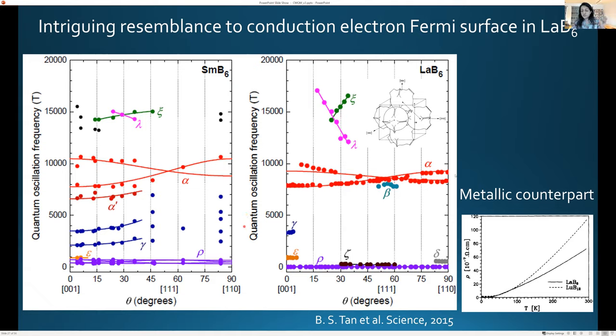So instead, we notice something interesting: the frequency size and the angular dependence is somewhat unexpectedly similar to that of lanthanum hexaboride, which is the conduction electron counterpart of the samarium hexaboride. This is where, as I spoke about right at the beginning, one has hybridization. The F hybridizes with the D, that's what gives you a gap. In the lanthanum hexaboride, the F electrons are gone, so all you have is a conduction band. So the hybridization gap is gone as well. You just have a conduction band, the Fermi energy crosses it, and one has these isotropic Fermi surfaces.